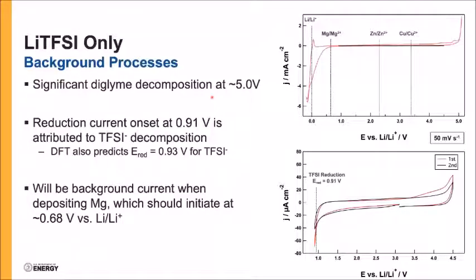And just to show what the background chemistry looks like in this electrolyte, we have a more or less featureless electrochemical response across the whole window of the different working cations we want to look at. Although we do see the onset of reduction current at about 0.9 volts versus lithium, which matches some predictions from DFT results that I'll discuss in a little bit. And so we do attribute this to TFSI reduction.